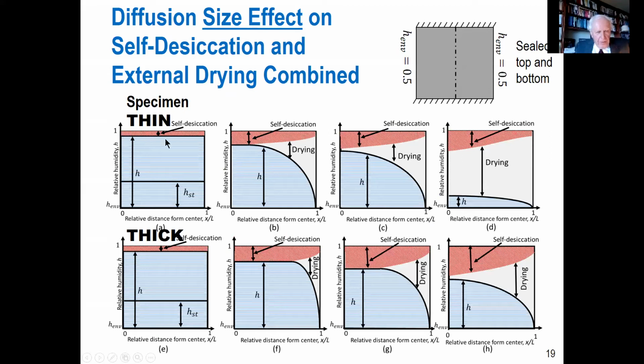This is the red. And this is humidity which is not yet affected by self-desiccation. So it is at the beginning small, and as it grows now, if the specimen is exposed like this on two surfaces from the side, this is the center line on the left, this surface. There is a drying front propagating inward. This is error function, roughly parabola.